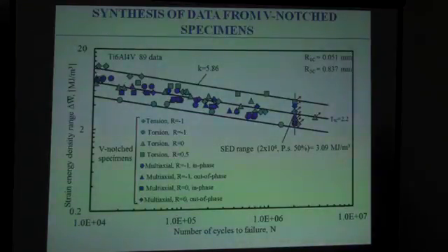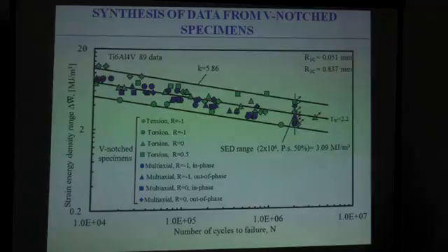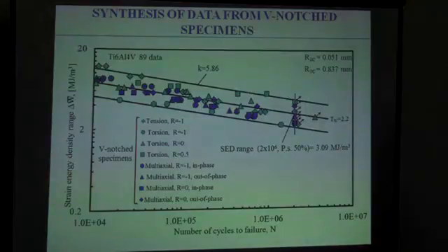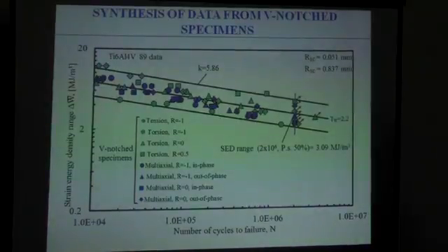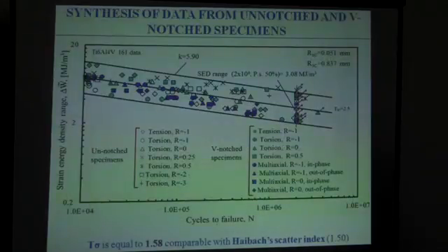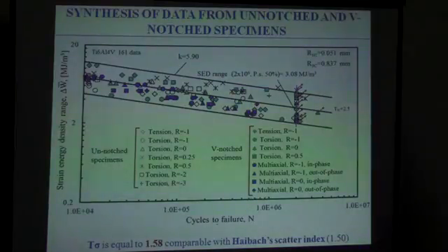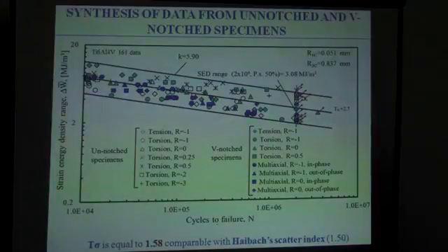Applying the criterion, we were able to summarize all the data from notched materials inside the scatter band. We have almost 90 data from different combinations of loading. This is the synthesis only of the notched materials, and the scatter band in terms of the strain energy density is 2.2, so it is very good. If we want to obtain a stress scatter, we have to take the square root of this value, so it is a very low value. And considering all the data together, we have approximately 160 new results with a scatter band which, if we convert in terms of stresses, is almost 1.6, which is comparable with IIW scatter bands for usual fatigue.